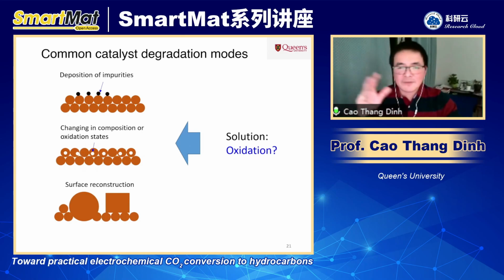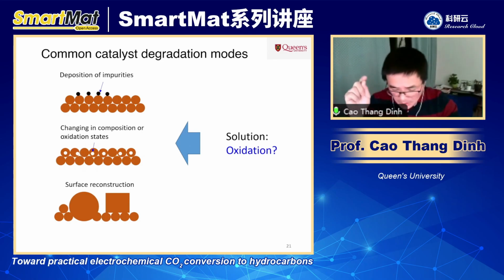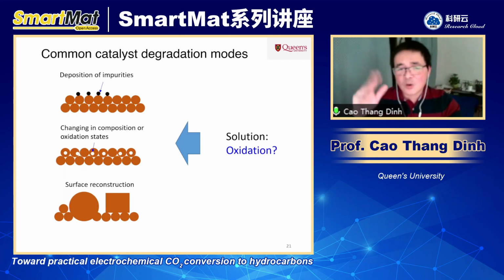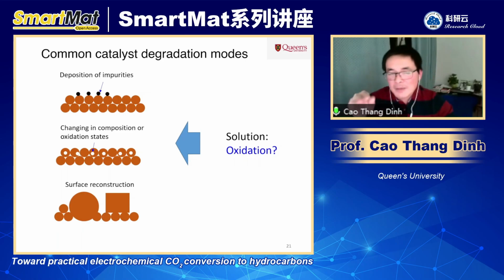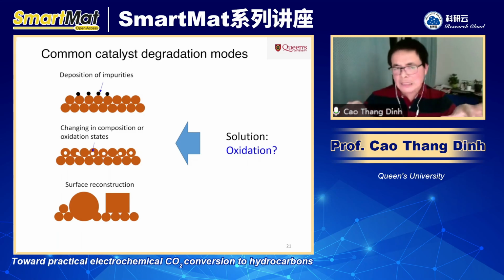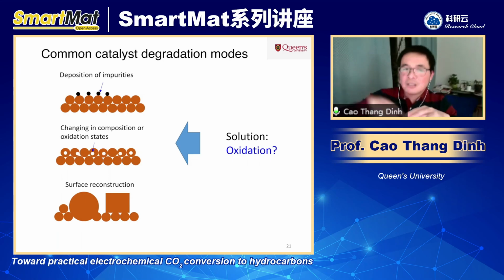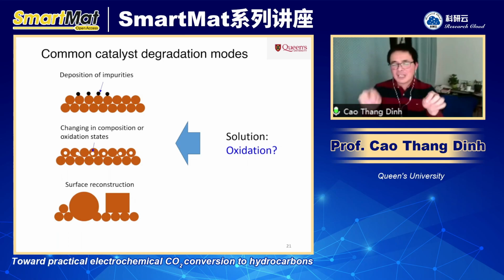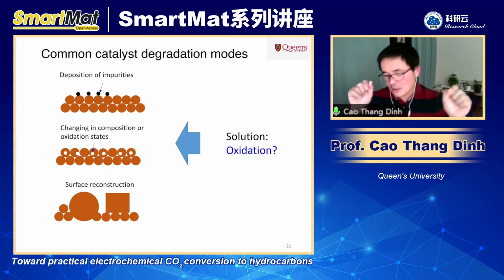Like if you run copper oxide, it's going to reduce to metallic copper, like zinc or other catalysts. Right? So it's changing the oxidation state here. Another thing, the last one, is quite common for copper catalyst: the surface of the catalyst itself is reconstructed. So it changes the morphology, it changes the surface of the catalyst, which leads to a change in the product selectivity. We know that the nature of the active site depends on the configuration of the atoms on the surface. And if that configuration changes, the selectivity will change.